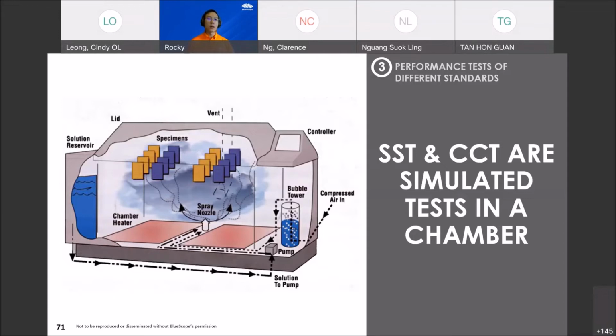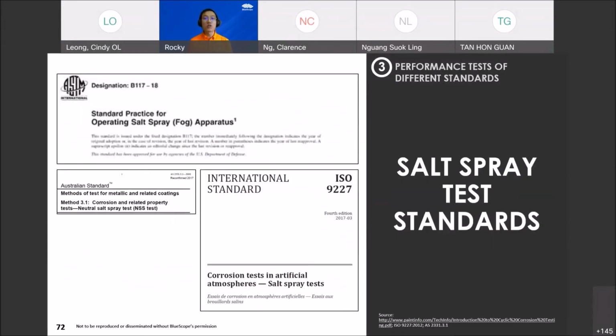All right, so let's talk about salt spray test first. Salt spray test also has its own standards. All right, so there's the American standard, ASTM B117. There's also the international standard, as you can see here, ISO 9227. Right, and there's an Australian standard also, a much more granular one, I think AS 2331 dot something. Right, all these point towards salt spray test, with slight variations. So again, we have to be specific when talking about all these test methods. Even in the production test, they also specify which test they want to follow.